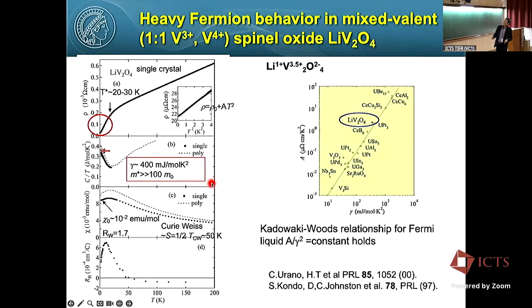Okay, so here is a summary of the physical properties of lithium vanadate. There is a crossover at some 20, 30K, and that indicates transport becomes coherent below that temperature, and at low temperature you see a beautiful T-square dependence down to T equals 0. And more importantly, the specific heat coefficient gamma is as large as 400 millijoule per mole K squared, comparable to cerium and uranium heavy fermion intermetallics.